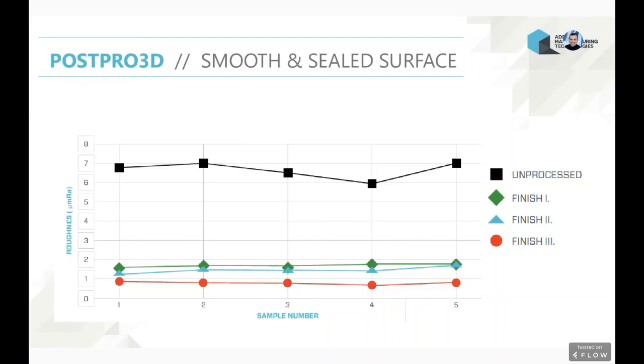These different sample numbers that we have there are different parts from different batches printed in a multi-jet fusion process with nylon 12, and they've been treated with different conditions. For all the purposes of this talk, just call it finish 1, 2, and 3. Call it a light, standard, and heavy finish. But it's just the different parameters within the PostPro3D treatment to be able to achieve a very specific surface roughness value and to do it repeatably.